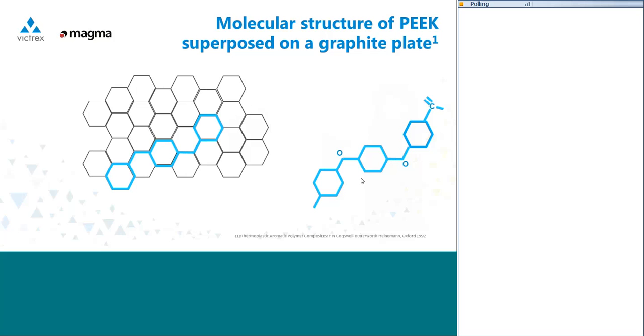The reference for this is at the bottom of your screen. You'll be able to pick that up if you download the presentation later. Now, it is an approximation because of the form of the molecule being three-dimensional, but it does demonstrate clearly the close compatibility of these two materials, and it's known to be associated with enhancing crystallinity around the fibers and so on. So clearly these two materials are very compatible, but it also needs saying that a good composite is also very largely due to the way that it's manufactured, and you need excellent fiber wetting, very low void content, and so on. So with PEEK matrices at least, we have a very high performance interface between the two constituent materials.